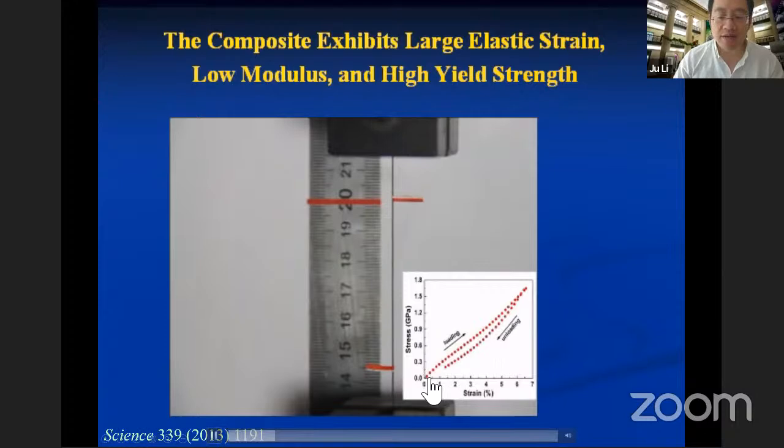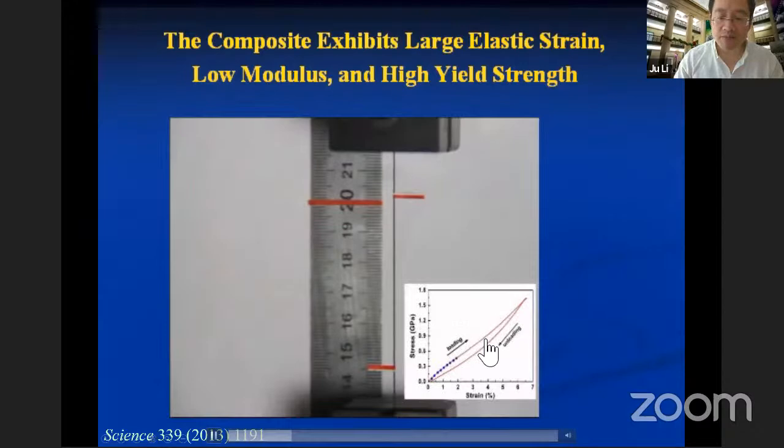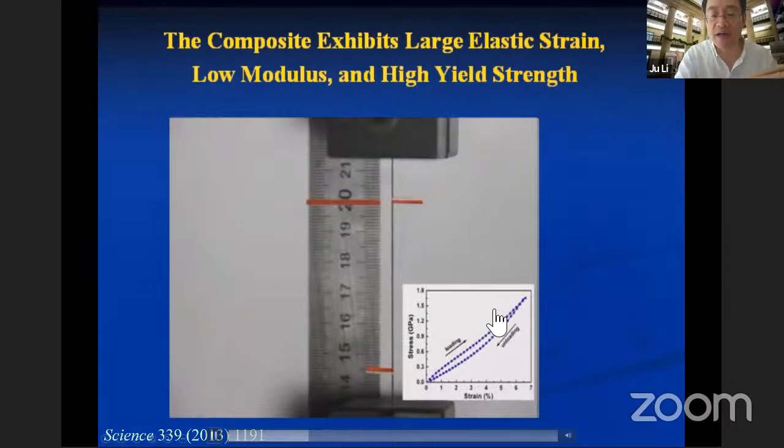Okay, so that's the first cycle. And there is some energy dissipation in the nitinol, but overall, it's pretty linear looking. And this is the 20th cycle. So the effective modulus is very low. It's like 30 gigapascal. Initially, when Li Shan was doing this research, he was thinking of orthopedic applications because you can have the